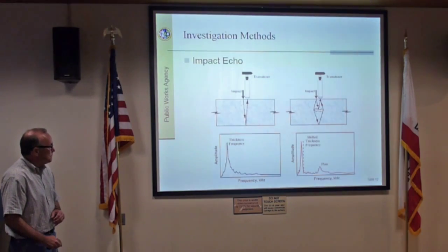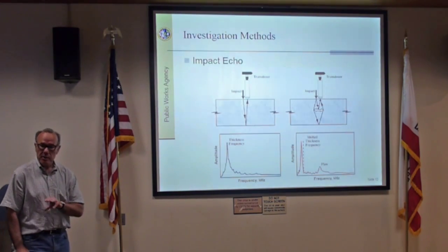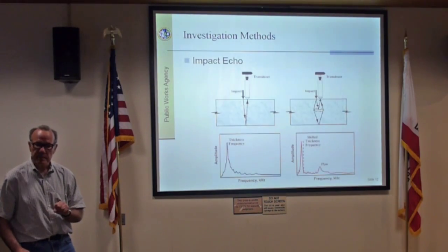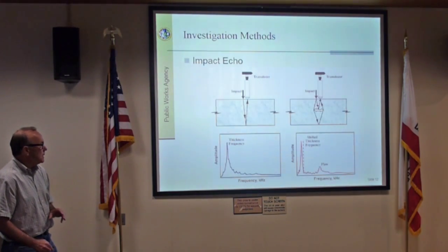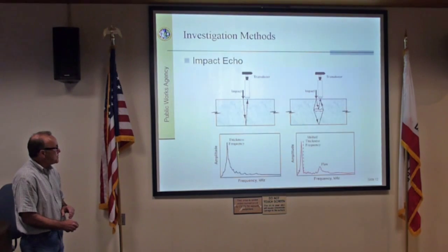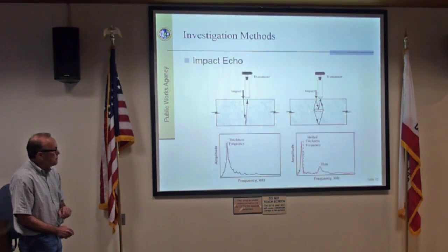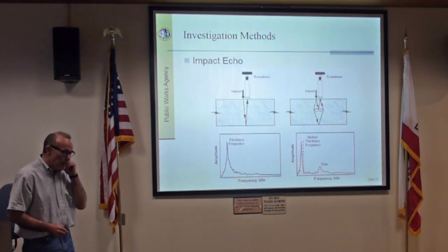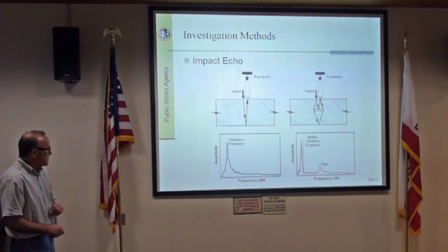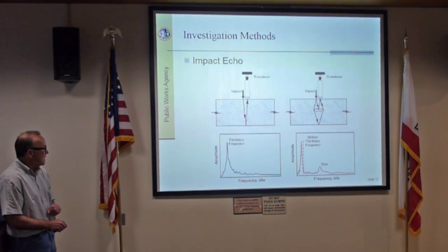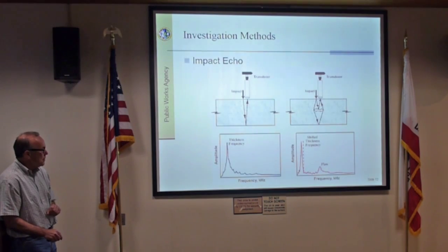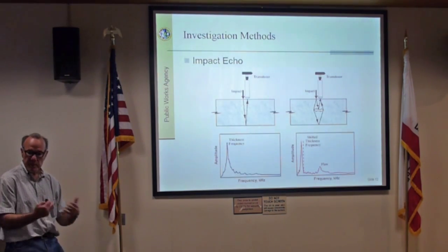The impact echo method we use doesn't detect corrosion. It's like ultrasonics for concrete. We impact the surface of the concrete and it sends out what we call a stress wave, literally a sound wave, through the concrete. Wherever there's a defect, we get a reflection off that. The reflection is fairly easy to see. You can see this signature here where it's a very sharp peak. That tells us it's solid through this. But here we get a shift and some other higher frequency peaks. That tells us the concrete's not solid.